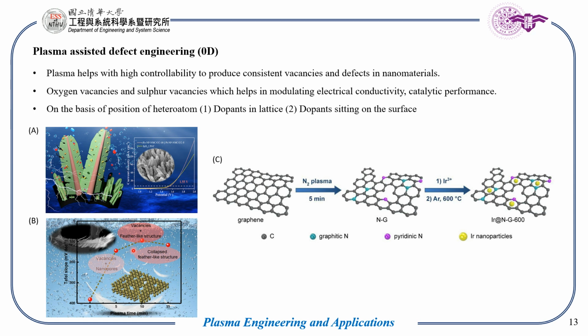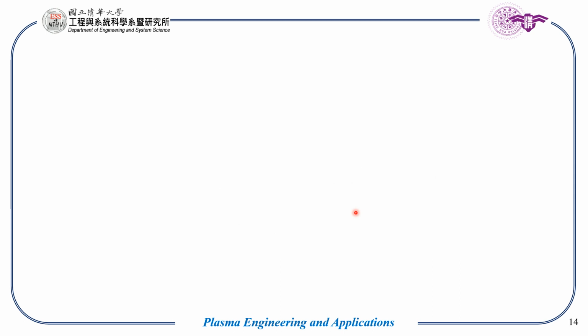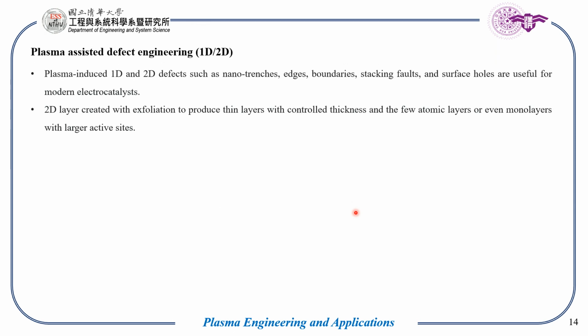In the last picture we can see graphene nanoseeds with doped nitrogen atoms, where RF, that is radio frequency, nitrogen plasma was used, and ultra-small iridium nanoparticles were sputtered on it, and this was further used to generate oxygen from this material. And now we will talk about 1-dimensional or 2-dimensional based defects that are being followed.